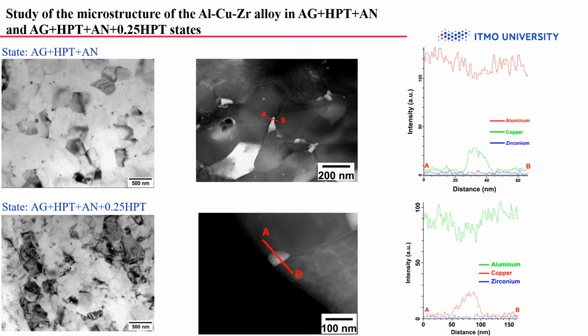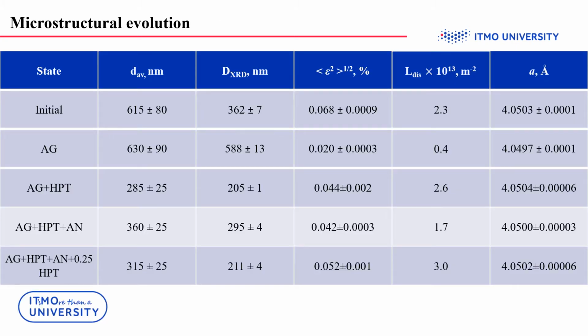To better understand the observed phenomenon of increasing ductility by deformation, we studied the microstructure of the alloy after annealing and subsequent deformation. It was found that in both states the grain size remained practically unchanged. At the grain boundaries there are still precipitates of the copper phase, the size of which increased to 60 nanometers. The main microstructure change is a decrease in dislocation density after annealing and a substantial increase of it after subsequent additional deformation.